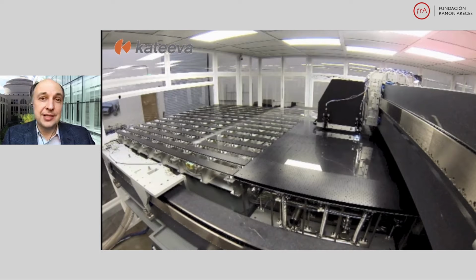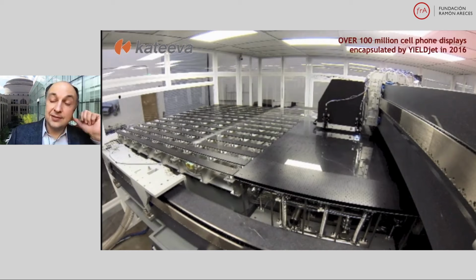If you're going to make technology that people can then use and sell the TVs you're going to make out of these, the challenge is immense to make a tool like this. And indeed, industry has never done it at this scale and using semiconductors that are organic, not conventional. So the tool was eventually delivered. And by 2016, over 100 million phones were encapsulated in that year. Now over 100 million cell phones are encapsulated every month, if not more, using this technology. If you have an OLED screen on your cell phone, it is very likely that a tool like this built it, a tool by Kateeva, a small startup that grew into a dominant tool provider for a very large industry.